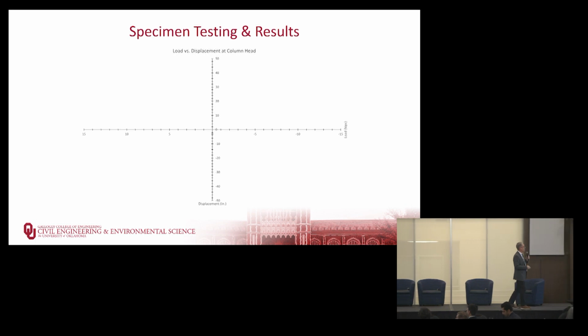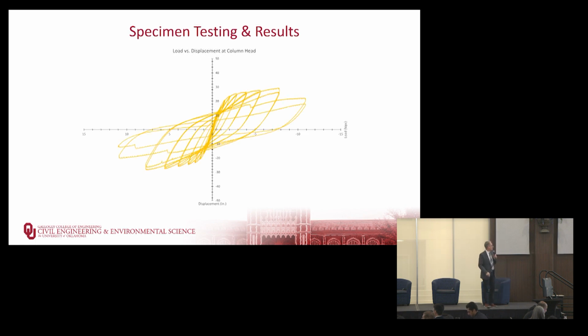So then we look at our plots, right? Engineers, we love plots. This is going to have displacement on the horizontal axis up to 15 inches, so the marks are 5, 10, 15. Load either compression, pushing out, or tension, pulling back on the column all the way up to 50 kips. And this is our typical hysteresis loop for a column tested with cyclic loading. This is our reinforced concrete column.